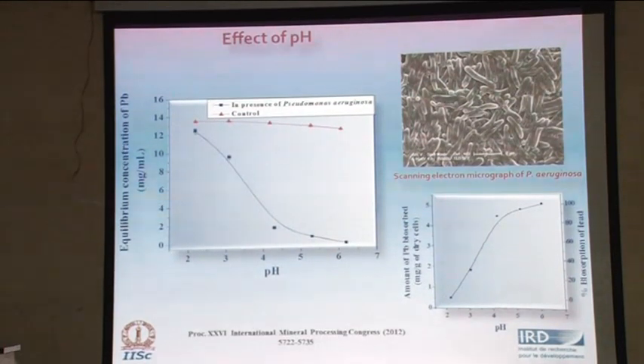So we have seen that in a controlled experiment as a function of pH, if you look at the stability of, in this case, lead, you will see that the lead is quite stable up to pH 6. But in the presence of the organism, you are able to capture the lead, and almost 100% biosorption of lead takes place.